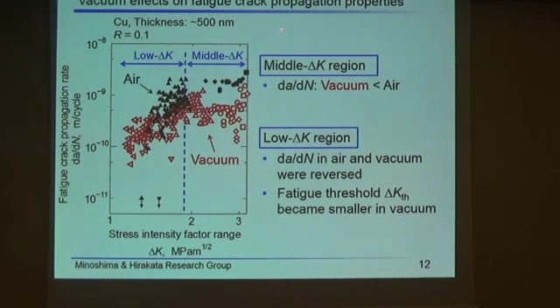In the middle delta K regions, da/dN in vacuum is smaller than that in air. In contrast, in the low delta K regions, by decreasing delta K, da/dN in air and vacuum are reversed, as shown in these figures. Moreover, fatigue cracks in vacuum propagated below the fatigue threshold in air, as shown here. So this indicates that delta K threshold became smaller in vacuum.